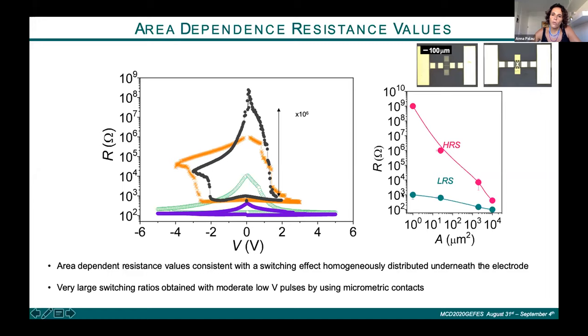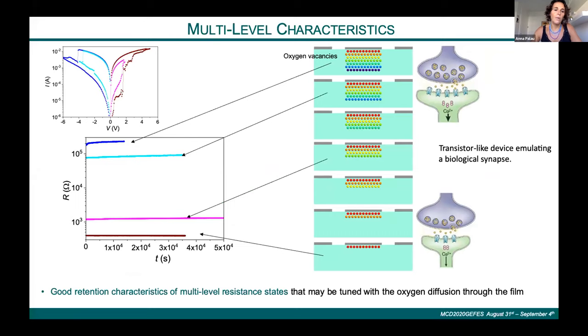And also we observe that very high ratios of 10 to the 6 are obtained with micrometric contacts, which would be also higher if we go to nanometric contacts. So this would be very good for the applications.